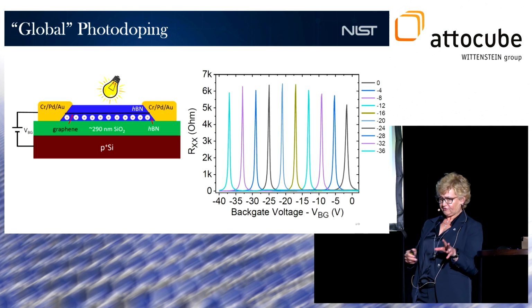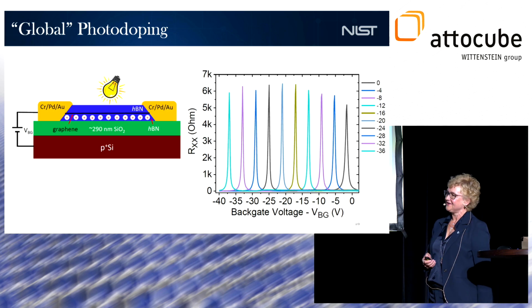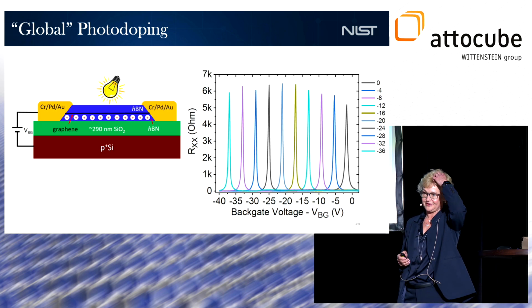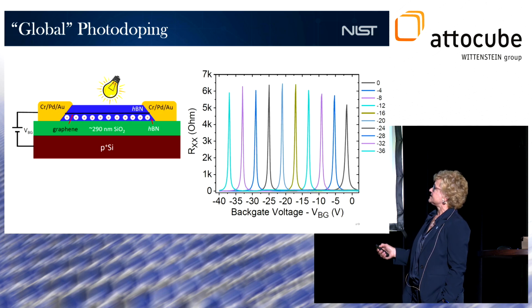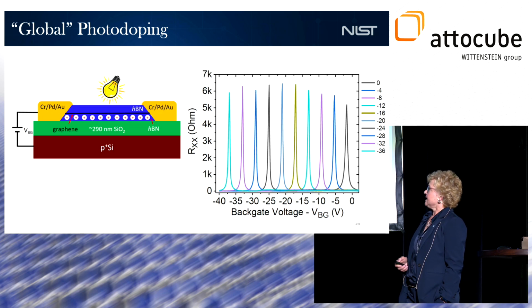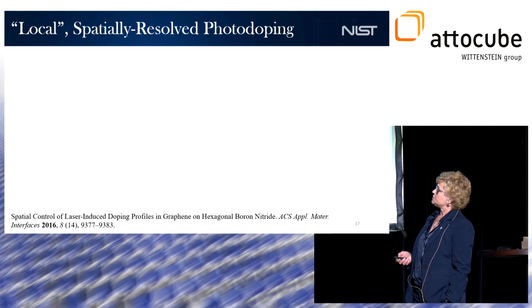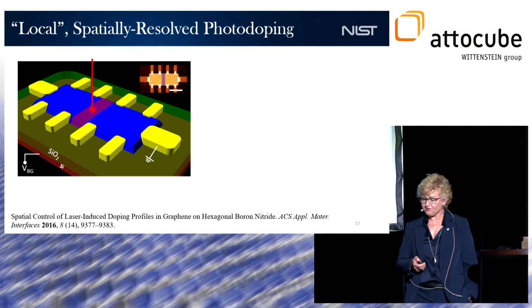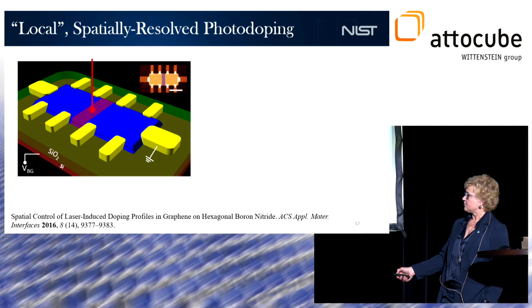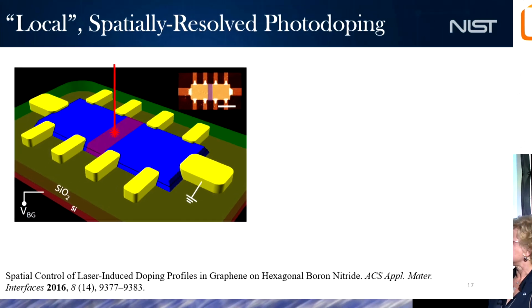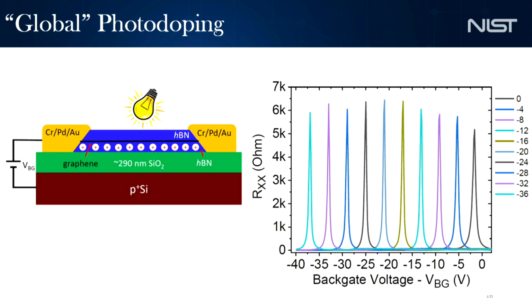I was quite surprised by this, as even finally we had to go call the electrical guys and be like, all right, we're doing something wrong. But so what we think is that there is some ability to do global doping. Also, we were able to do what we're going to call local, spatially resolved photodoping. And as it turns out, of course, as we then went to the literature, this has been seen before. The hypothesis is that the defects in hBN, here they're labeled as positive defects, are interacting in such a way that they're affecting the conduction, the properties of the graphene bulk.